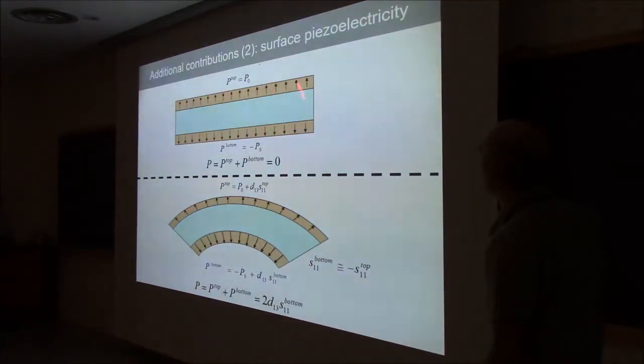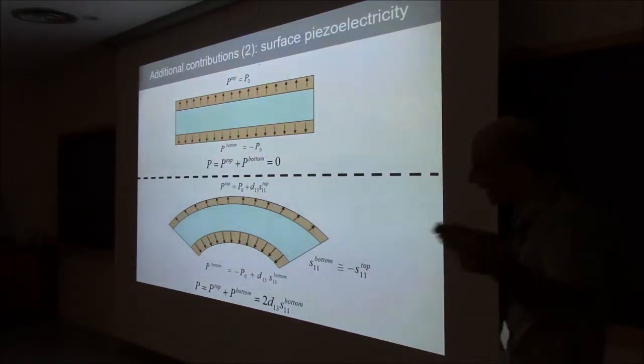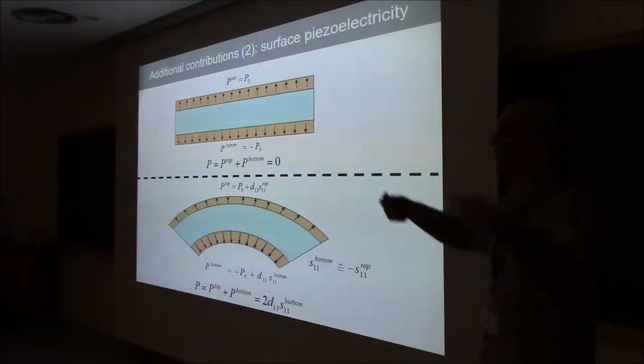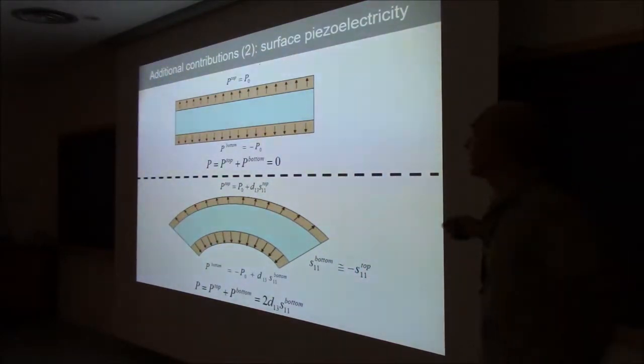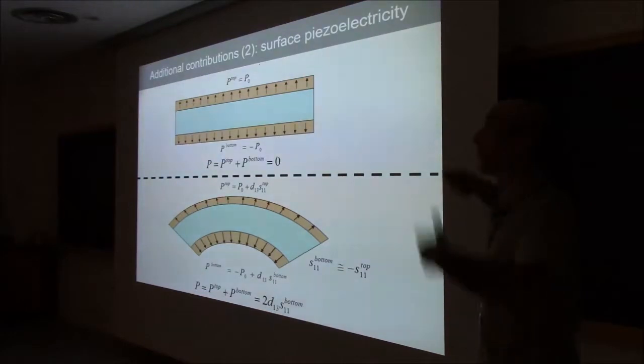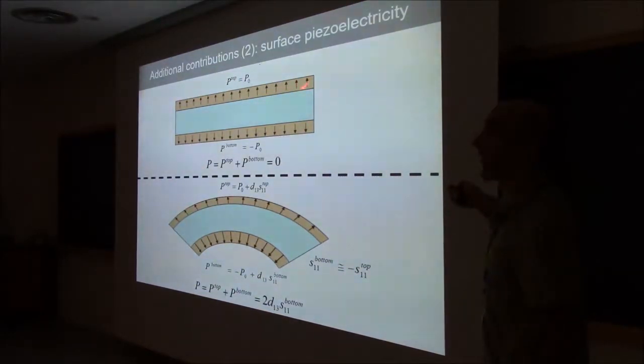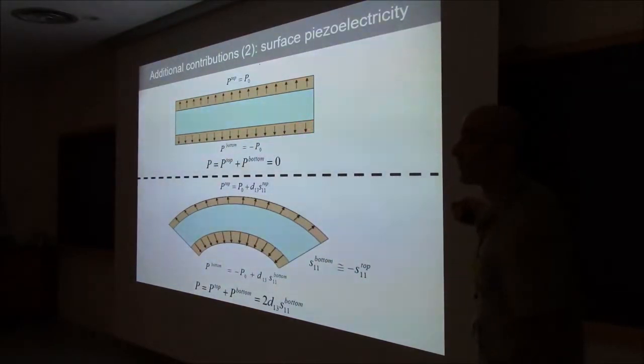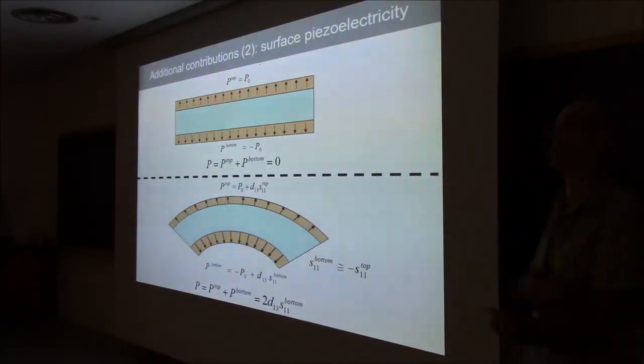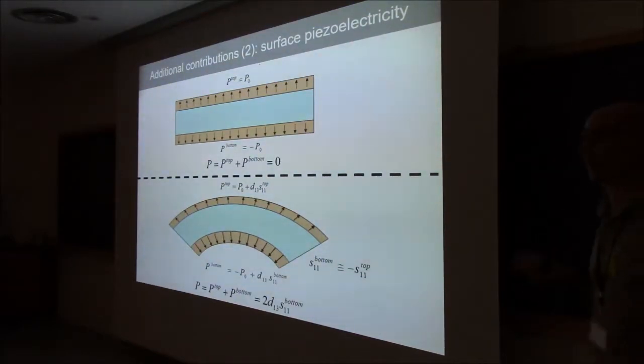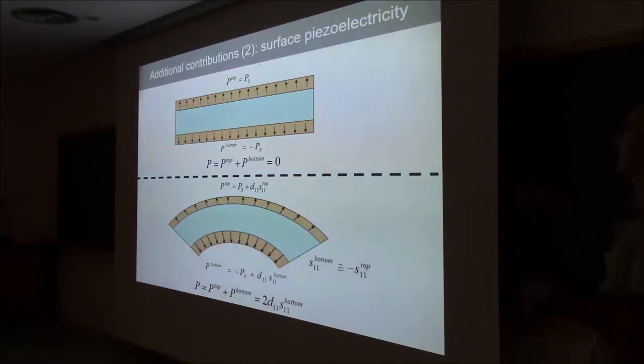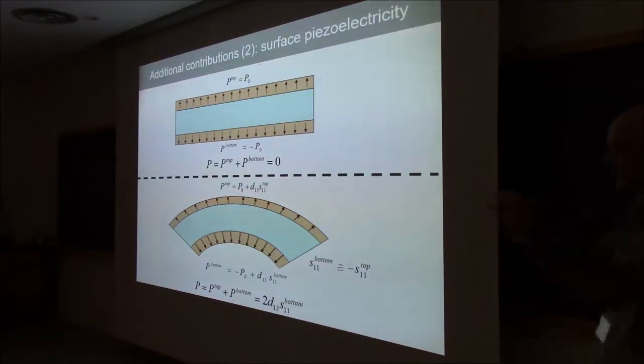Okay, and the piezoelectric coefficient of the surface, let's say, points in this direction here, and it points in exactly the opposite direction on the other surface. Now, if I take this crystal and I stretch it or compress it homogeneously, the piezoelectric change in polarization here is identical and of the opposite sign to the piezoelectric change of polarization here. So the two surface polarizations cancel each other, and you will not measure anything. However, if I take the same crystal with the same surface piezoelectricity and I bend it,